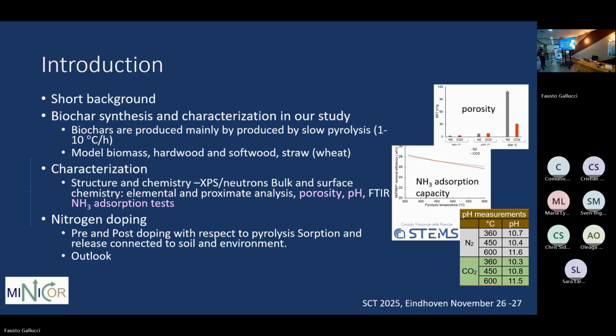So a short background. The biochar synthesis in our case concerns pyrolysis and slow pyrolysis, at a temperature increase rate of about 10 degrees per hour. The model biomass we use is hardwood, softwood, and straw. The characterization is based on XPS and neutron bulk and surface diagnostics, and chemistry analysis by elemental and proximate analysis. We also do porosity, pH, and ammonia tests, but I won't cover these because there's not enough time, and those are done by our collaborators in Italy, who do a wonderful job there. They report some FTIR data.